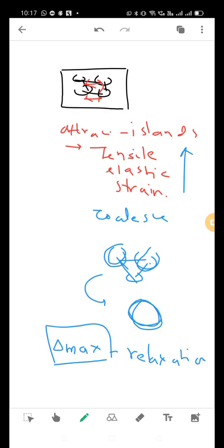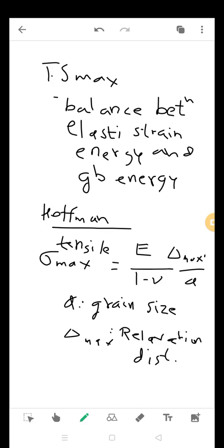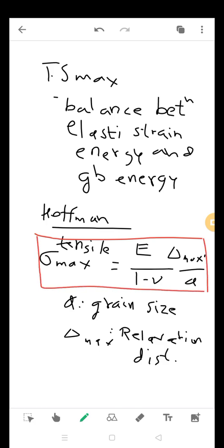So we have got this Hoffman's equation. Let us look at another one. This is the most vital equation. Elastic modulus has a role here, Poisson's ratio has a role here; these are material properties. It is inversely proportional to d, so the lower the grain size, the higher will be the maximum tensile stress. And it is directly proportional to delta max, because the further the grains are, the higher is the tensile strain, because the more distance they need to travel to get near to each other and to coalesce.